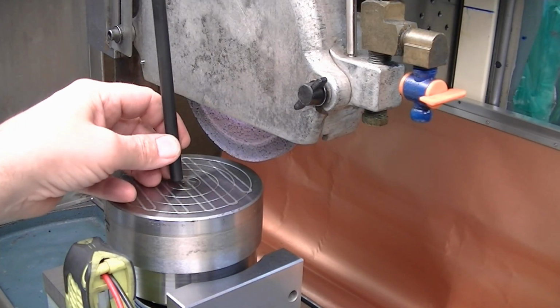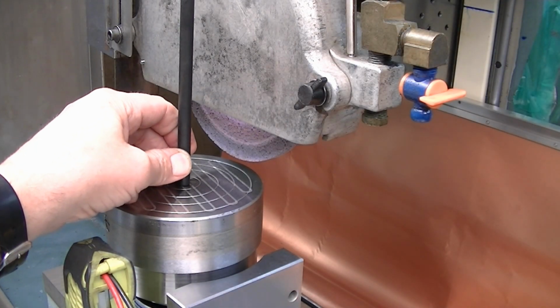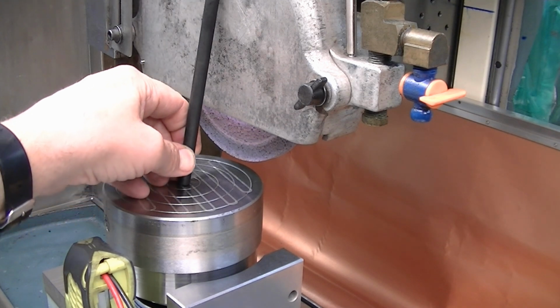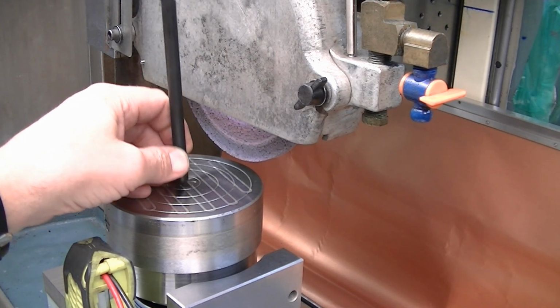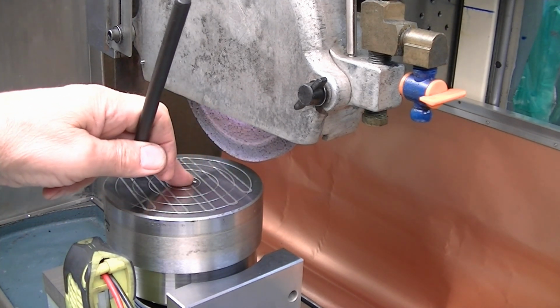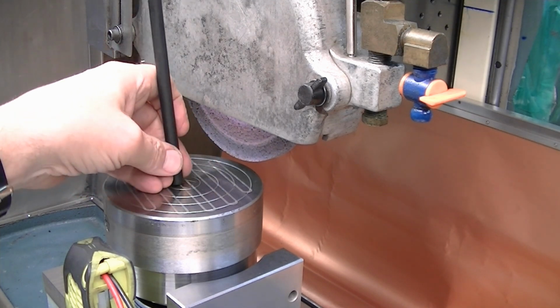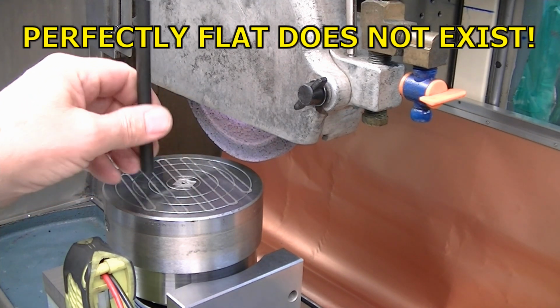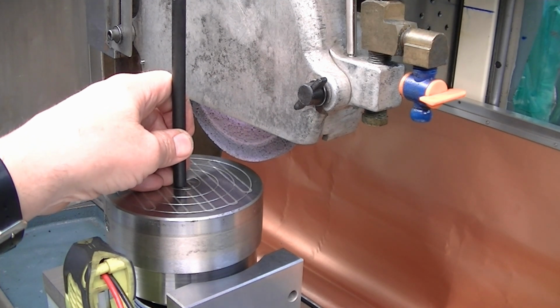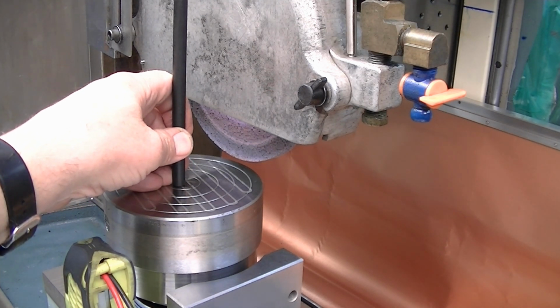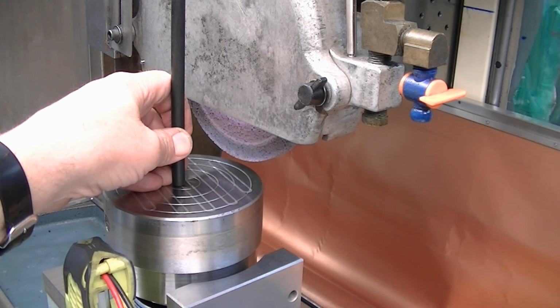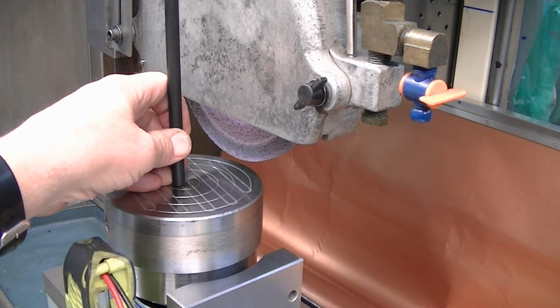Now, geometry. The axis of the spindle, whether it tilts like this or this, is actually going to determine whether or not you grind a concave cone, convex cone, or grind a perfectly flat part. That's why the tilt adjust of these needs to be able to adjust in very fine increments and repeatably if you want to be able to tune your grinder in to grind very flat parts.